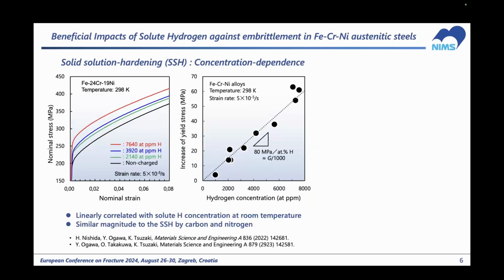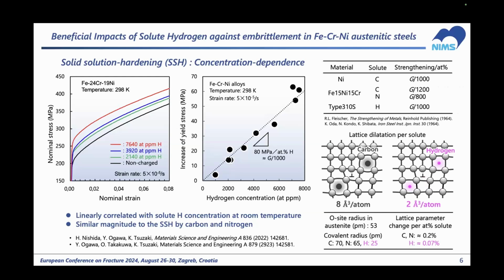So what is the trigger of such a strengthening and ductilization effect? The first reason is, of course, solid solution hardening by hydrogen, which monotonically increases the yield strength. The magnitude of strengthening reached almost 80 megapascal per atomic percent of hydrogen, and it is linearly correlated with the solute hydrogen concentration. What was notable here was that the magnitude of this 80 megapascal strengthening was quite equivalent to that when we added carbon and nitrogen in austenite as alloying elements.